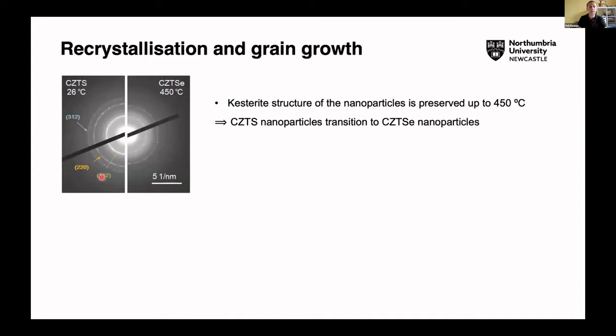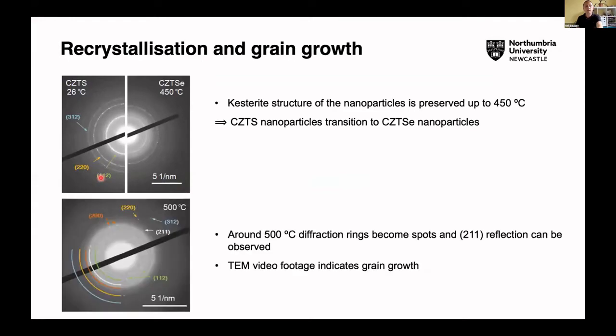And then here's just another representation of that really. You've got this kesterite structure of these nanoparticles, which starts off at room temperature, and it stays in that phase as you incorporate the selenium. So at 450, you have CZTSe nanoparticles. Something interesting then happens around 500 degrees. These diffraction rings start becoming spots. And so we see an improvement in the crystallinity.